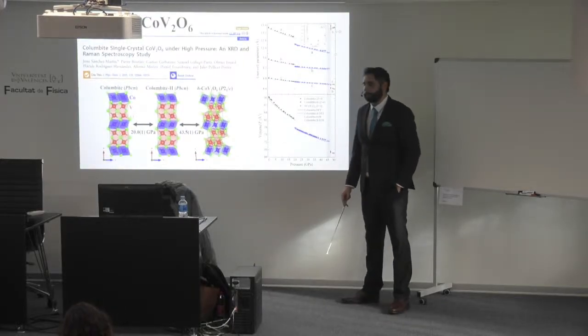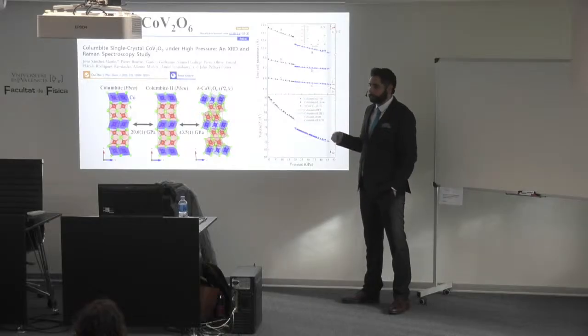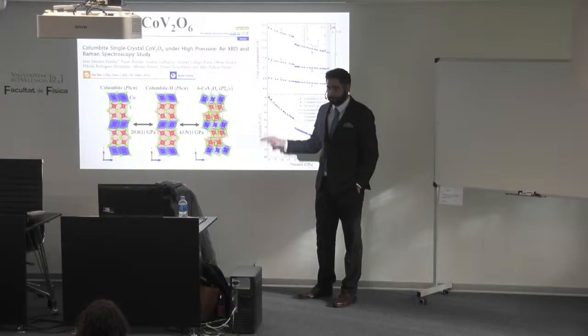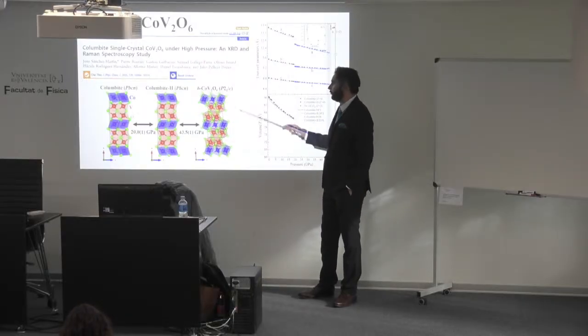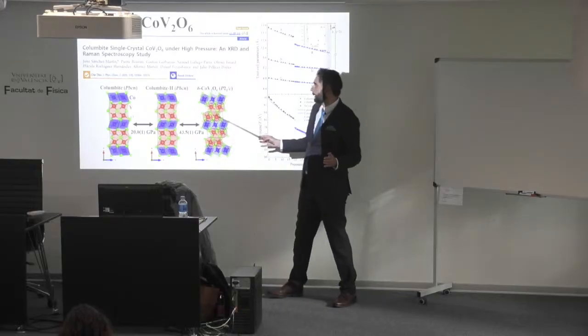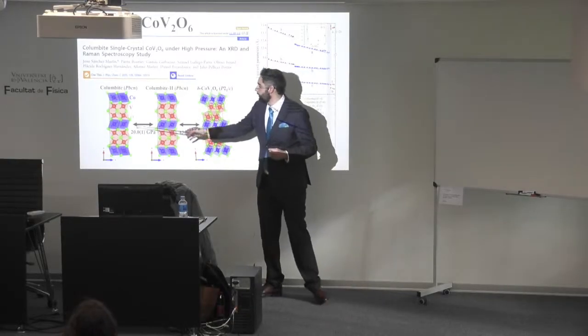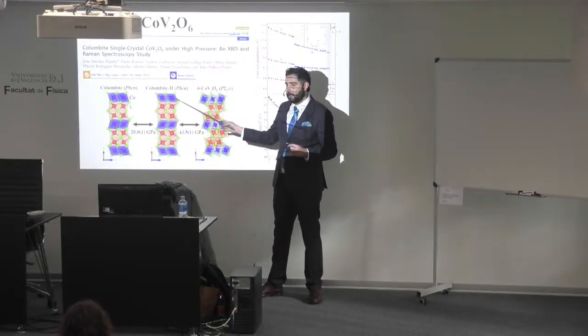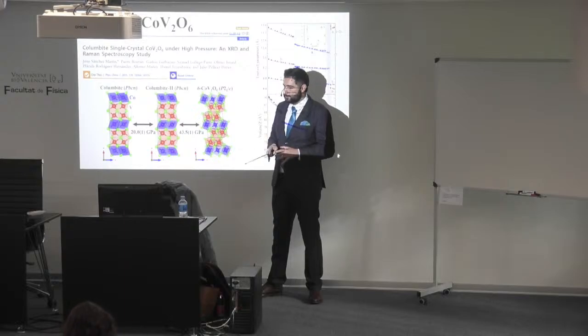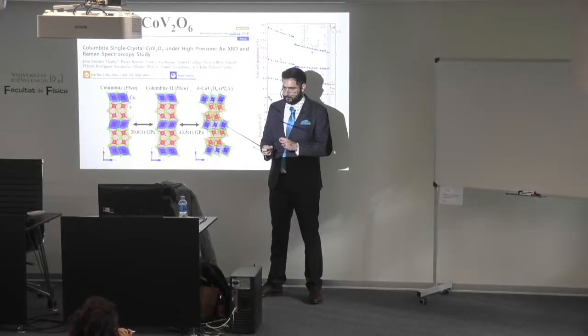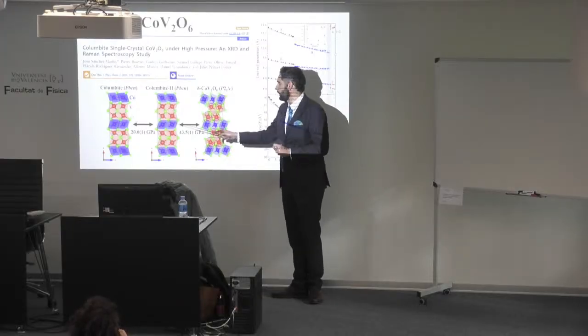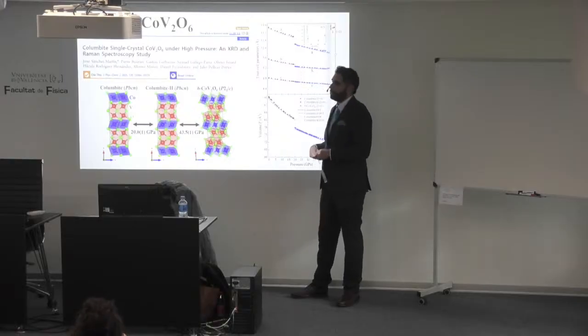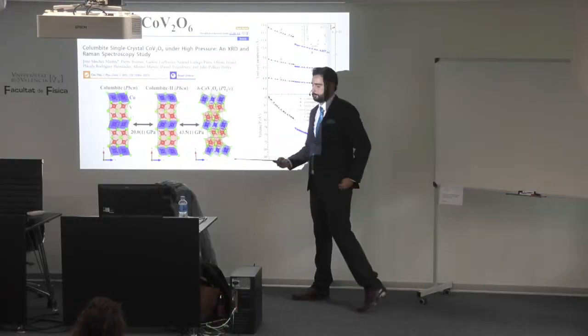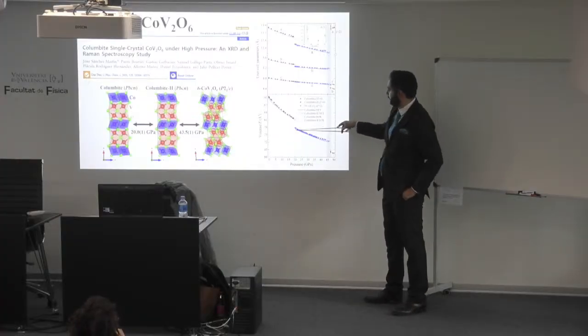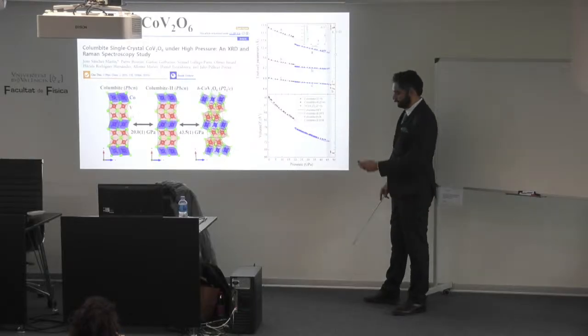This one, the cobalt metavanadate, should be brannerite in nature, but we got columbite single crystals. This is a metastable phase. And we performed some Raman experiments without knowing what was going to happen. And we saw, XRD and Raman experiments, sorry. We saw that at 20 GPa, it goes through an isostructural phase transition. So it stays at the same structure, but the atom positions shift in a way that I'm going to explain later. And then at 44 GPa, we have another phase transition, this time to a monoclinic structure. We see here that even though the structure is the same, it has a noticeable volume collapse, and yet the last one is totally different.